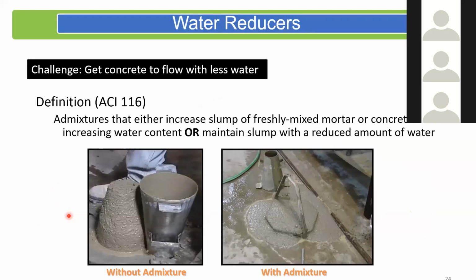Now, the most fundamentally important admixture that we use is water reducer. And of course, the need for water reducer came up about 30 years back, 40 years back, when we realized that if I want to make concrete that has a high slump, then I need to add water, but the minute I add water, then I lose strength. So then people invented these water reducers. Initially, they were just simply water reducers, and now we have made these more and more complex, to the point where we've come to high range water reducers.